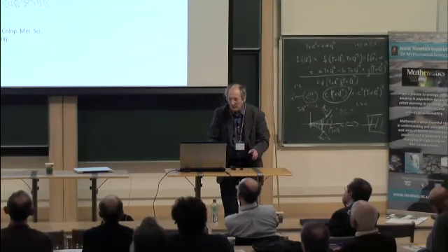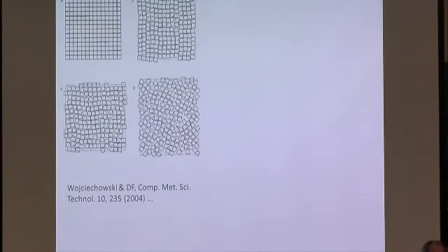So actually, in this case we looked at particles that have some intrinsic shape that might couple to the orientation, but not rod-like particles. Typically, if you talk about Onsager's model, then you have rod-like particles, and they can form, for instance, a nematic phase or possibly a smectic phase. But if you take square particles, in a two-dimensional system, then at very high density, clearly, it will form a square lattice. Well, I say clearly, it's not quite so clear, but you can get this kind of lattice.